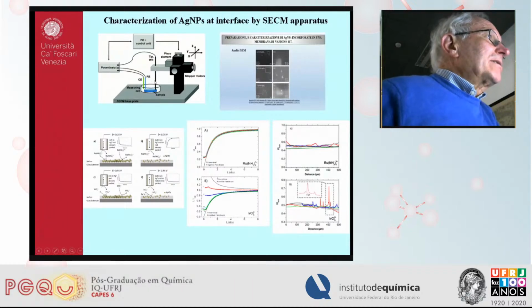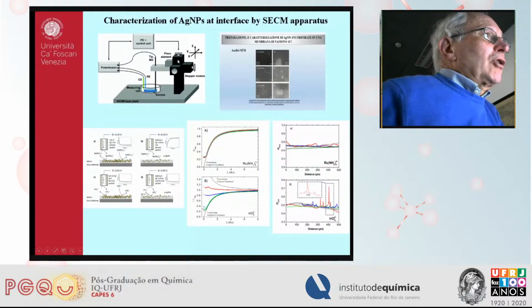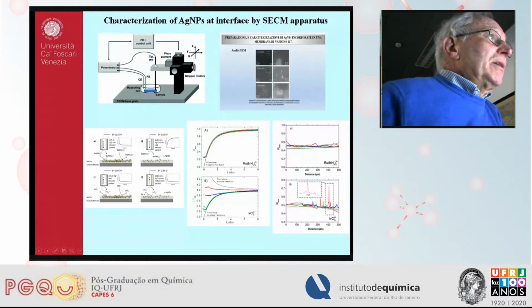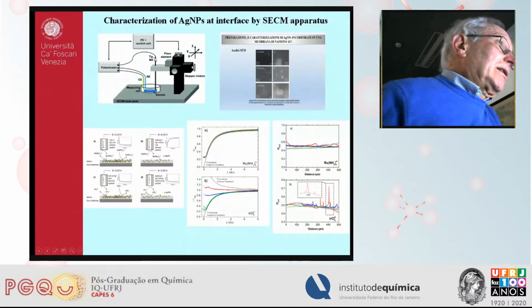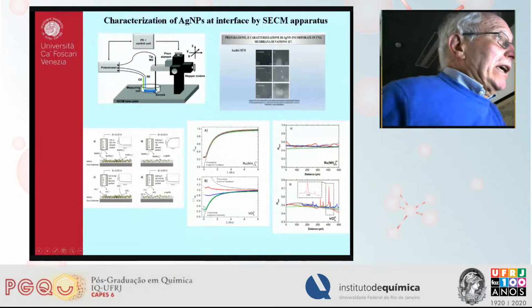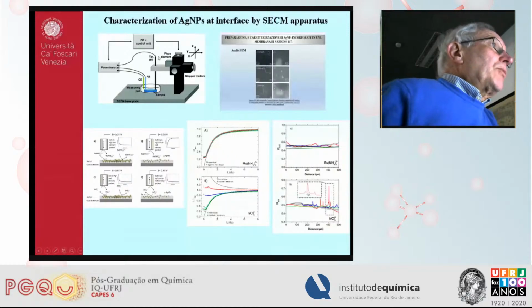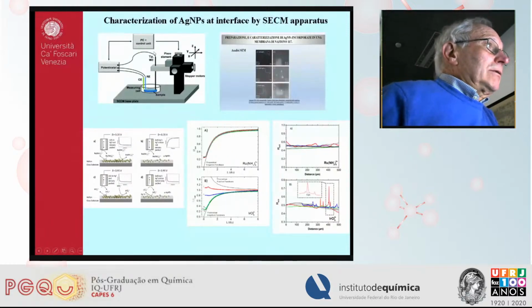which is moved in space by a system which can provide micrometer or nanometer resolution, and which can approach a substrate at very, very short distances. So this means that if we use a microelectrode and approach a substrate very close to it, we can make measurements at the interface between the material and the solution.